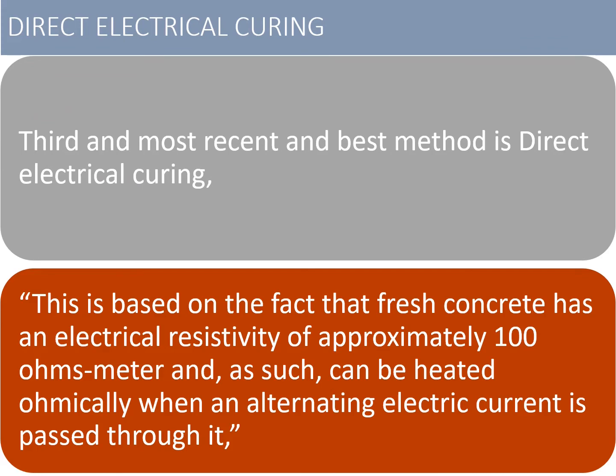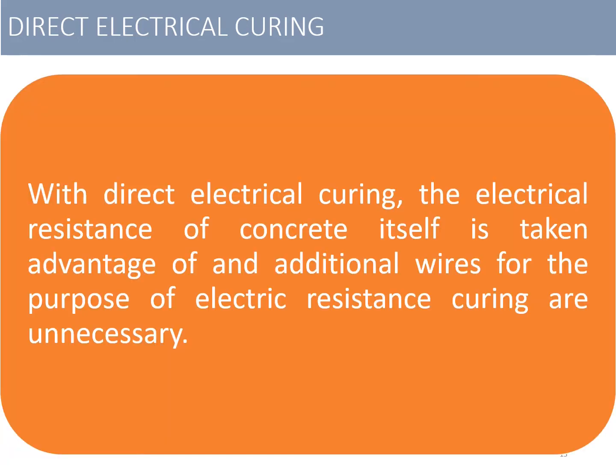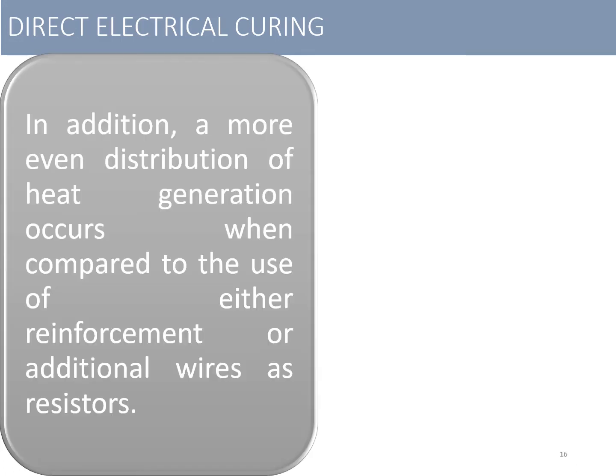This is based on the fact that fresh concrete has an electrical resistivity of approximately 100 ohm meters, and as such can be heated ohmically when an alternating current is passed through it. With direct electrical curing, the electrical resistance of the concrete itself is taken advantage of, instead of putting additional wires inside the concrete for the purpose of creating electrical resistance curing. In addition, a more even distribution of heat generation occurs when compared to the use of either the reinforcement or the additional wires as resistors.